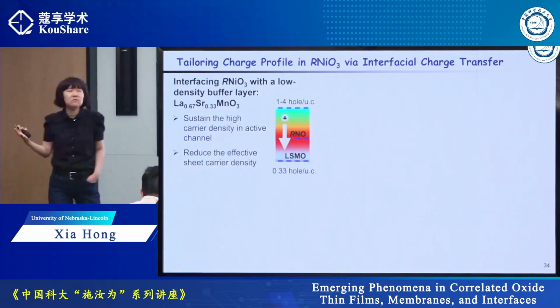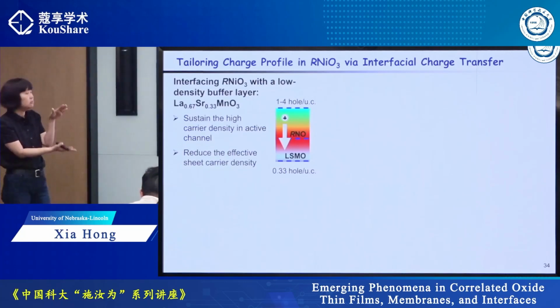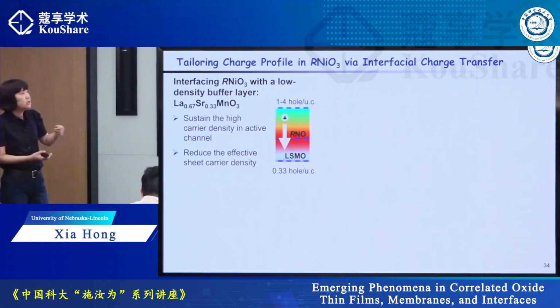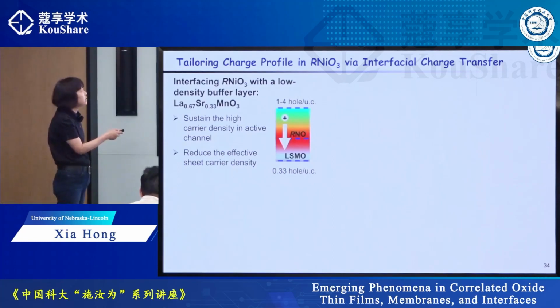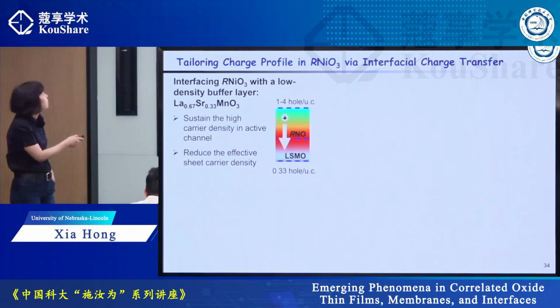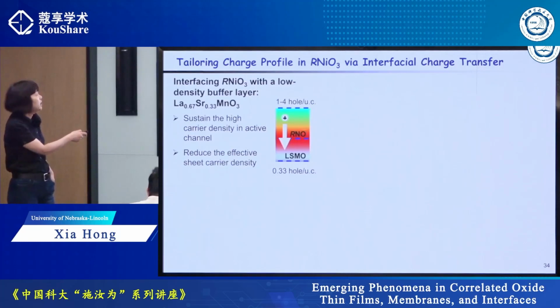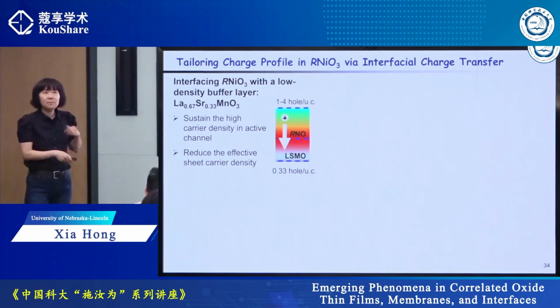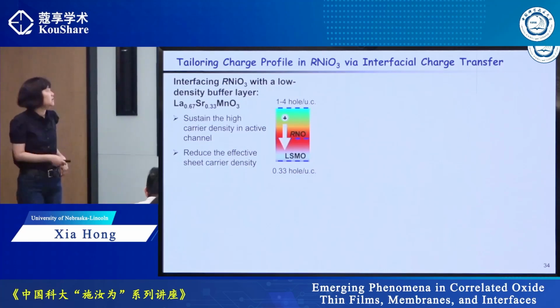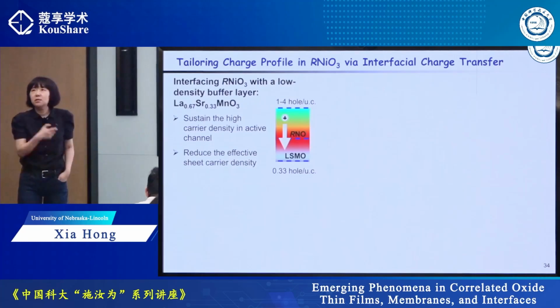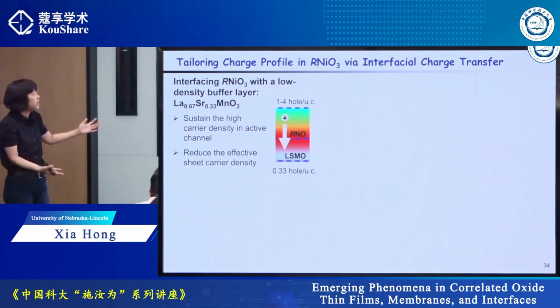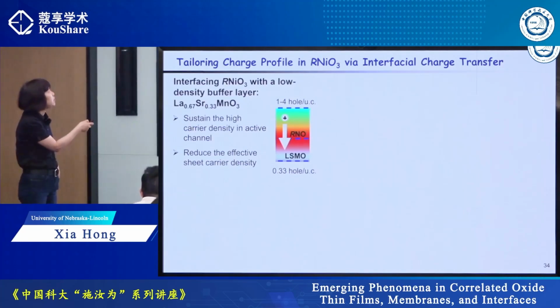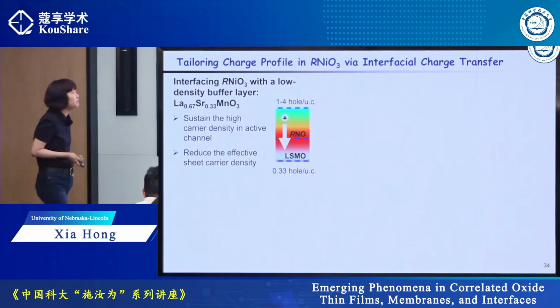So we thought of an alternative approach. The problem is that if I just reduce the film thickness, the sample becomes dead. If I make the film have lower carrier density, then it doesn't give me good scaling. So what if I can have a channel where the carrier density is not uniform? I only sustain the high carrier density at the interface with the ferroelectric gate, but dump the carrier density from the rest of the channel, so that I can still sustain a sufficient overall charge density to screen the polarization, but only the central part has high carrier density to be modulated by the ferroelectric.